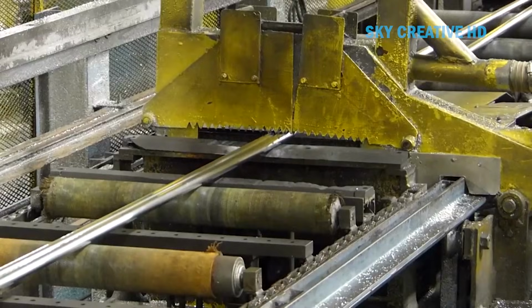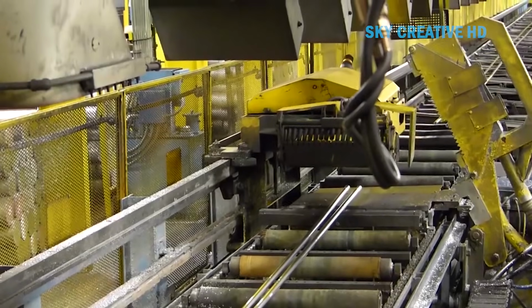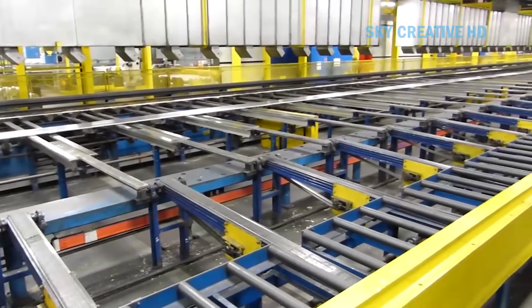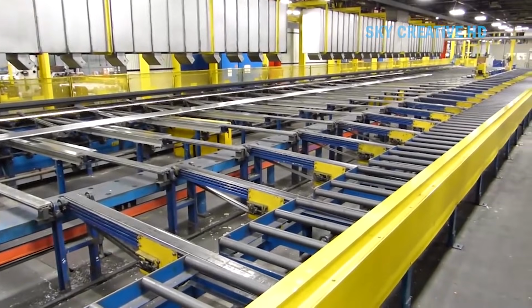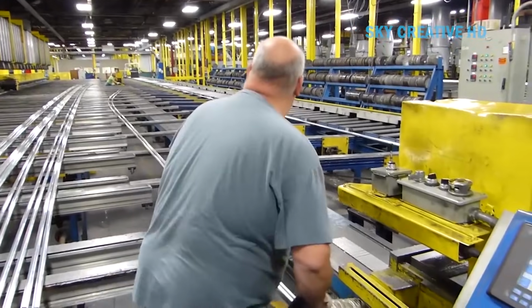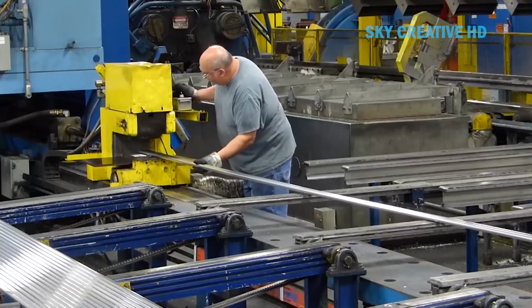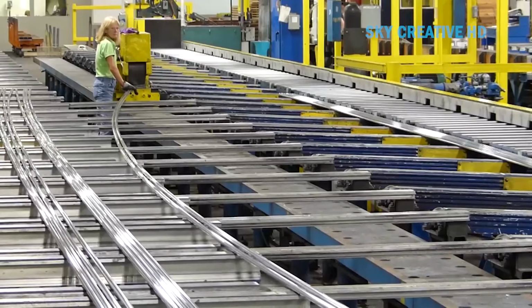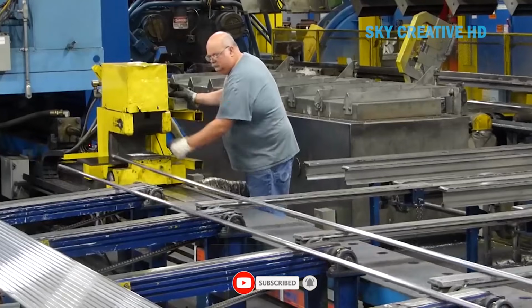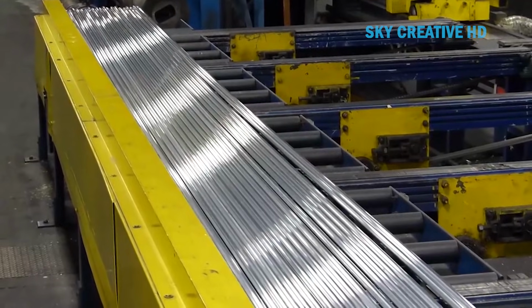The extruded length then moves to a stretcher, and this is an important step many people don't realize happens. The stretcher grabs both ends of the extrusion and pulls it straight with carefully controlled force. This accomplishes two things. It straightens any warping that occurred during cooling, and it relieves internal stresses that could cause problems later. The stretching force is precisely calibrated for each profile and alloy.